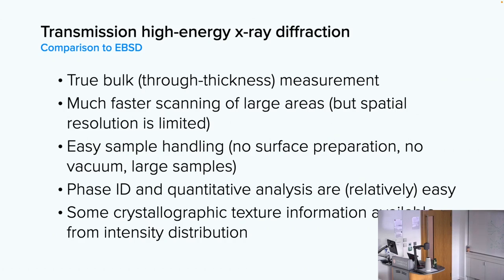So what do we decide to do instead? We turn to X-ray diffraction, because I'm an X-ray guy from a long time ago. In particular, we're going to do high energy diffraction, which allows us to operate in transmission. The big advantage there, the two biggest advantages, is that we get a true bulk through thickness measurement. We're equally sensitive to the front surface of the sample, and the back of the sample, and everything in between. We can scan large areas really rapidly for reasons that I'll show you in a second. But maybe the most important reason is that it places minimal demands on sample handling and on sample preparation. If the sample surface is a little rough, no big deal.